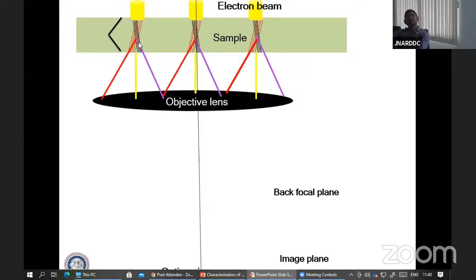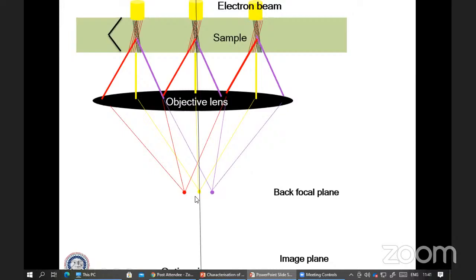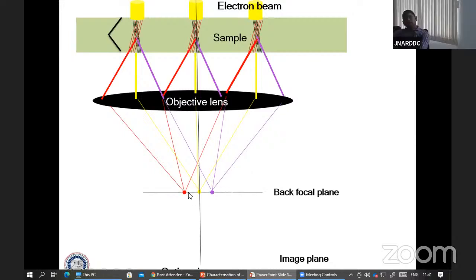Once your transmission electron beam falls upon your sample, this red one will be reflected and fall on the objective lens, and then it will be converged here and get a spot here. This is called a diffraction spot, and it happens at the back focal plane. This yellow one is parallel to the optic axis, so this is our transmitted beam spot, and the violet one will give you another diffraction spot. Since it is from a single grain, you will get a spot pattern here.